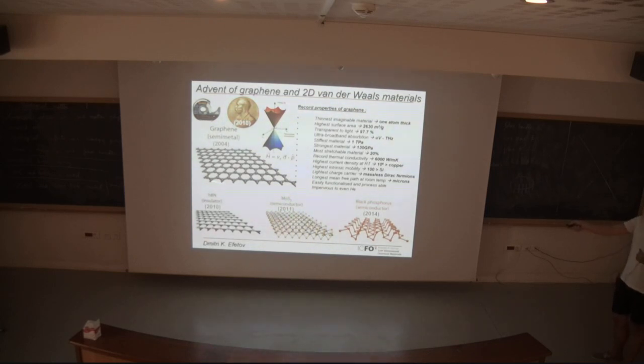So anybody of you can also do it after a couple of hours of training. You can extract a single layer of graphene. Conceptually, this was a very unexpected discovery, that you can extract 2-dimensional materials just like that. But the other immediate surprise was how good the crystallographic quality is. In principle, you can imagine that as you make stuff thinner and thinner, it would become very disordered and amorphous. But in graphene, it was not the case because it has this ultra-strong carbon lattice. The crystallographic quality is extremely good, and you can get single crystal flakes with almost no defects over tens of micron scales. So it's extremely high quality.